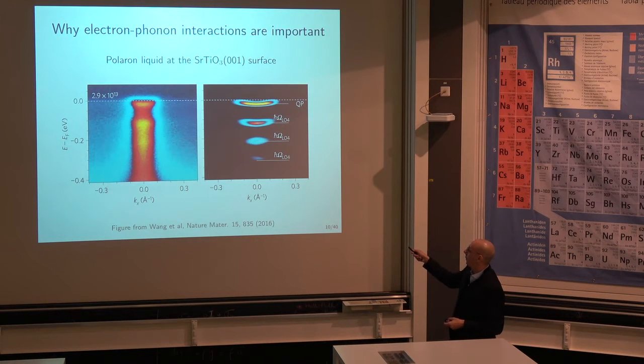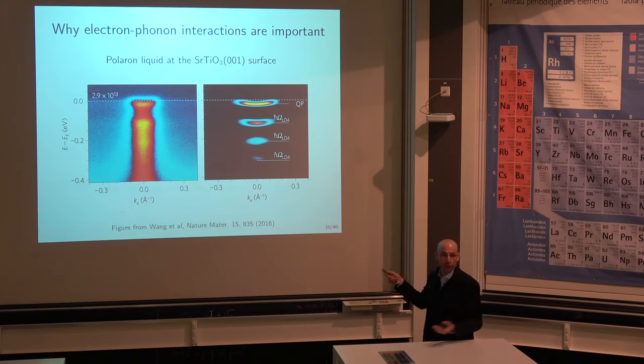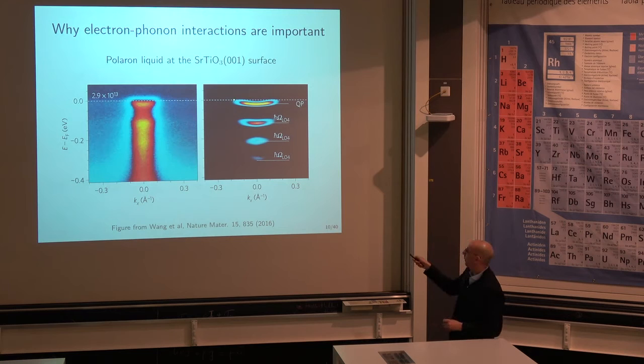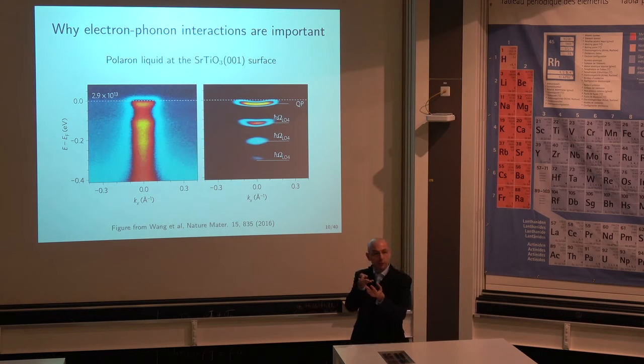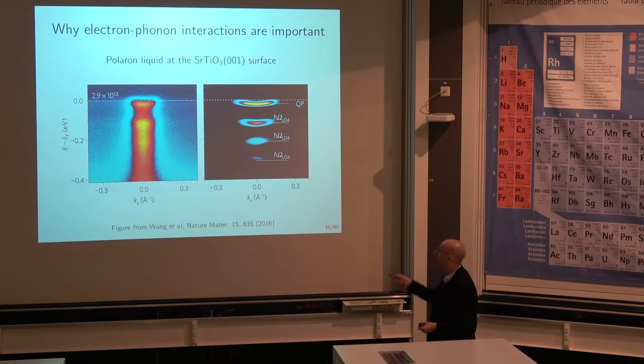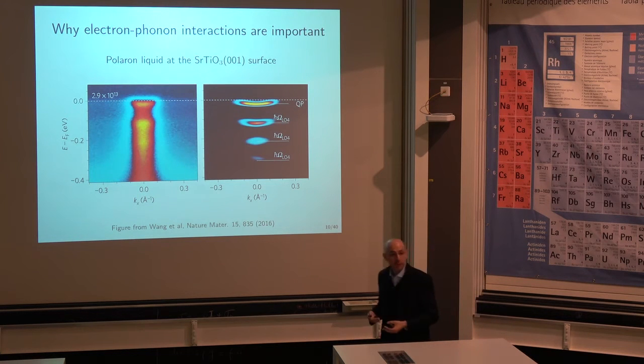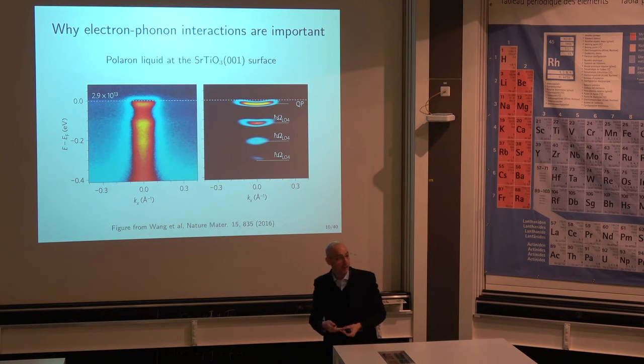So what this is essentially is a many-body band structure of strontium titanate, okay, obtained from angle-resolved photoelectron spectroscopy. I will say something more about this kind of structures. But what people were expecting basically is a little parabola here from the experiment. This would be the bottom of the conduction band. So if you dope a little bit the conduction band bottom of an oxide, you should see a little parabola. So that's what people should have seen. And instead, this experiment gave this object, then a replica here, another replica, okay? So this comes again because of electron-phonon interactions, all right?